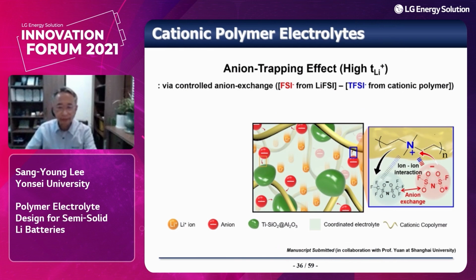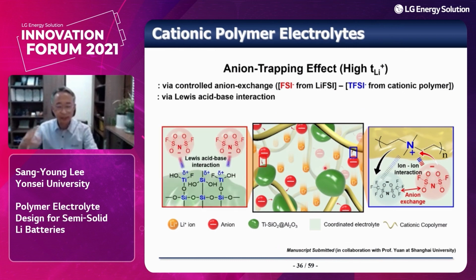Therefore, we can selectively capture the FSI anion from the lithium salt, which gives freedom to the lithium cations. In addition, to further enhance the anion trapping effect, we have incorporated inorganic particles based on Lewis acid interaction, like this.